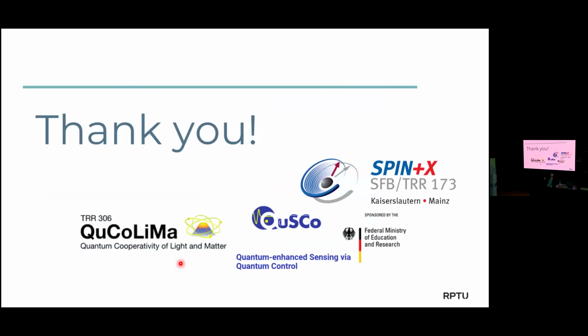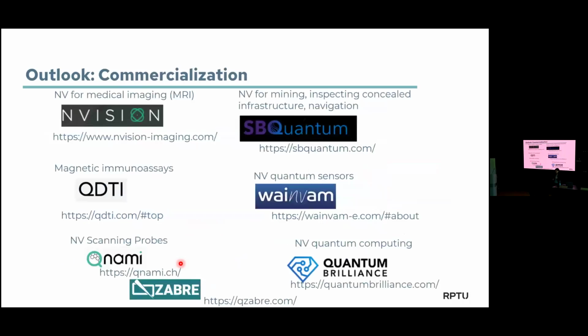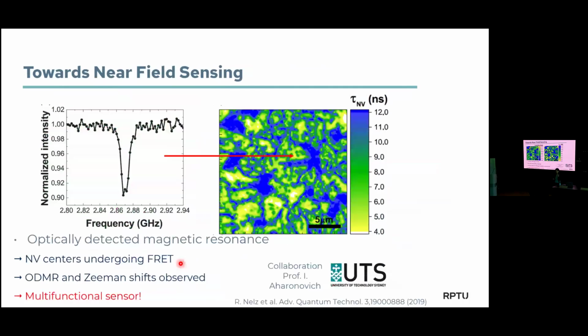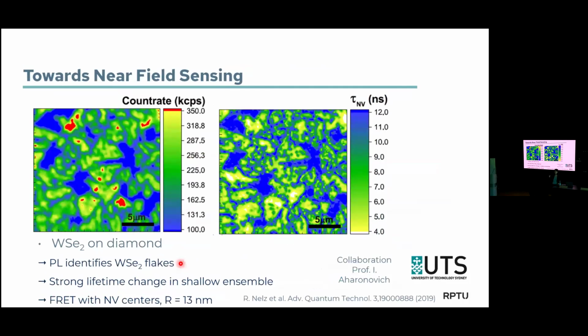Yeah, so you are also online, right? So when you do the magnetic sensing, of course, you have a single NV at the tip. When you were showing this near field, at least all of the results seem to be on an NV layer. So how do you do the local addressing then? In this case, we really did it as a proof of principle. So it's an ensemble of NVs, but it's not so many NVs in this case. We estimate we have about 10 NV centers in the focus.